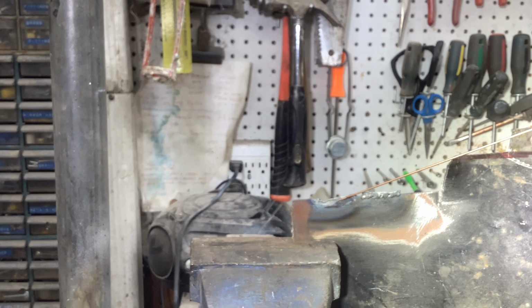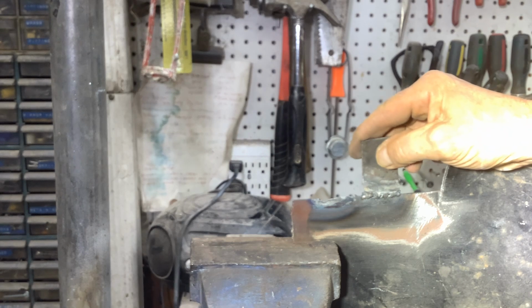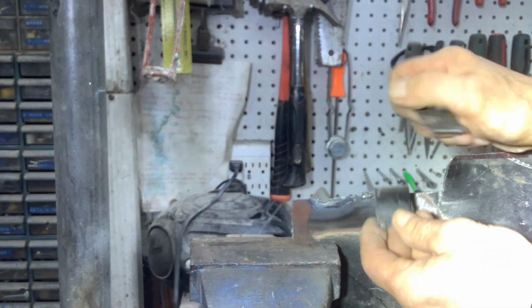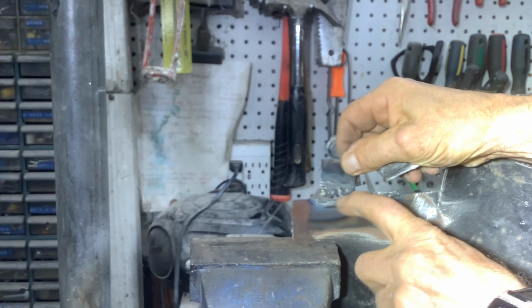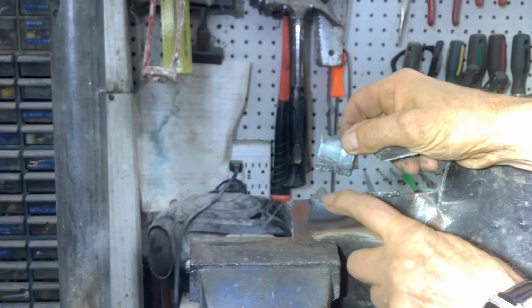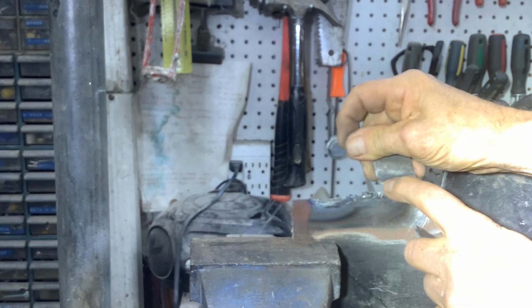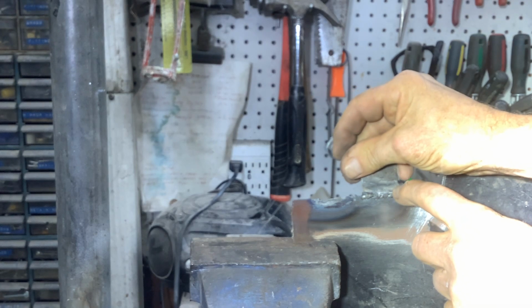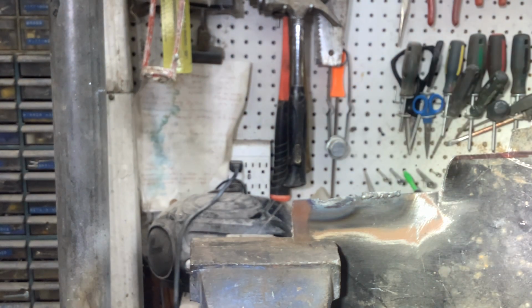I flexed it back and forth and it cracked here. Here it broke more along the weld. The weld wasn't as strong as on this side. See, this is more in the weld, and this is more outside the weld. This is completely flat here. This has still got weld on it here. So it broke more along the center of the weld. Okay, that's the benefits of annealing.